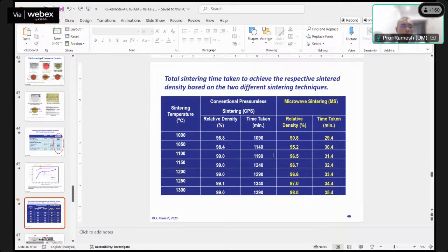I think what I want to highlight really is, if you look at 1000 degrees centigrade with conventional sintering, in order to get a relative density above 90%, it takes about 1000 minutes, as compared to microwave. To get above 90% dense, it takes only half an hour. So the advantage is there.